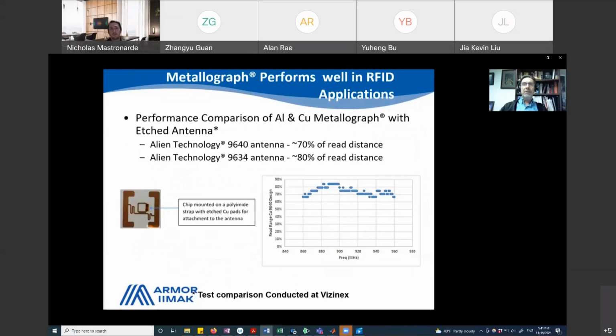Several years back, we asked our friends at Vizinex RFID to help us benchmark our thermal transfer printing processes against etched metal RFID tags. The read range of the thermally printed metallograph ribbons was 70 to 80% that of the read distance for the etched tags. At the time, conventional wisdom predicted that metallograph printed antennae with a thickness almost 2 orders of magnitude thinner than the etched antennae wouldn't have performed so well.